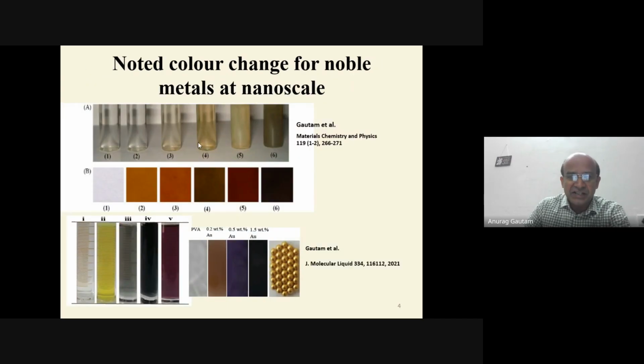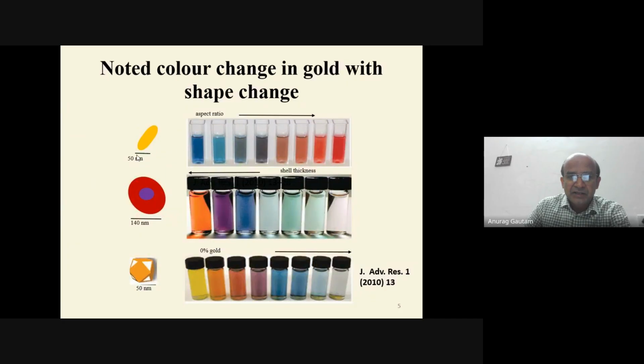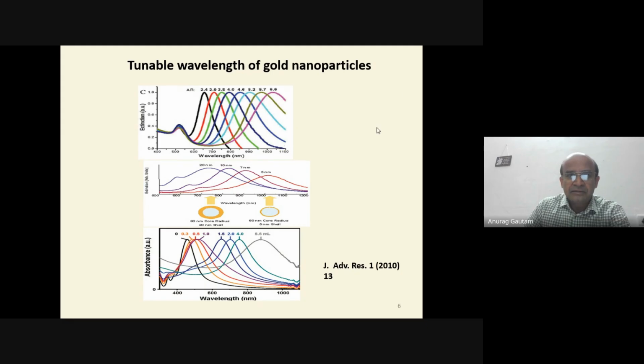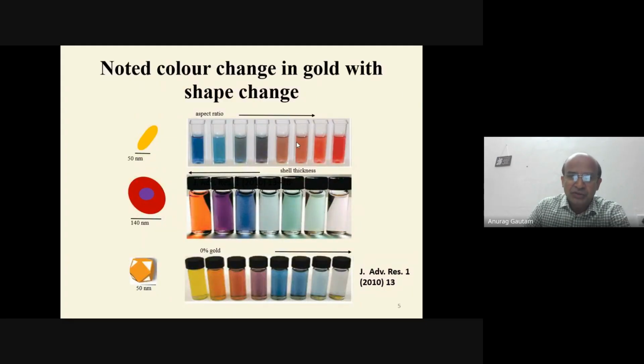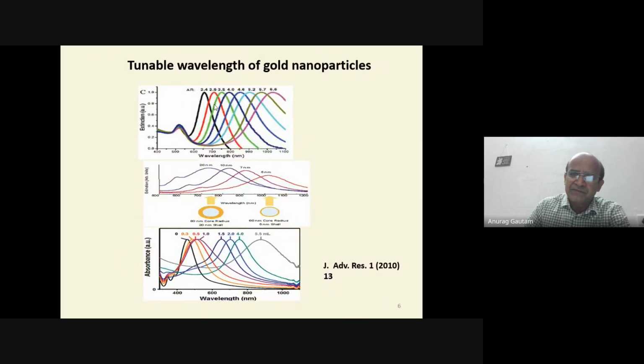Again, if we change the shape of the gold particle, for example to a capsule shape, the color can vary depending on the aspect ratio. The aspect ratio is length by width. So if you tune this, the color will shift. As the aspect ratio increases, meaning we make the particle longer and longer, the color will shift further this way. Similarly, if you coat it, you will see a different color. All of this is well described in the literature. So we are able to tune the wavelength, because during bioimaging for any optical purpose, we want a particular wavelength that we can image, or that can match the optical emission with the particular part of the body. That is the tunable wavelength of gold nanoparticles.